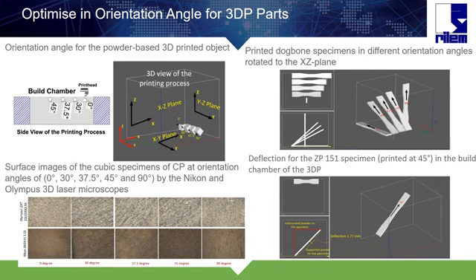Here, showing the orientation angle while printing has a major effect on the robustness of the product in terms of mechanical properties. It not only affects mechanical properties, but in large specimens it also causes deflection in the printed structures. That's due to the heavy bound powders in the specimen, and for example we can see it in the printed parts at 45 degrees and 37 degrees as well.